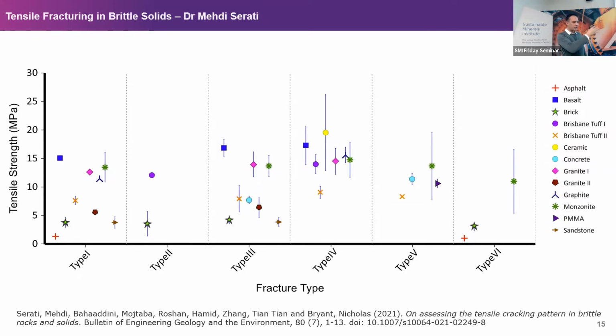So the question was, how come you get exactly the same type of product, like the broken sample, but in some of them the force at failure is 50% less. That's why we used a high-speed camera, and to our surprise, those samples that showed the lowest force at failure correspond to cases when the crack didn't start from the center, but rather started from one of the 2 ends. This suggests that although you may look at the sample, and you are not utilizing high-speed recording, you look at the sample, you break it, you get a single crack, it's all good, that's a tick. But the reality is how the crack is started, where the crack is started. It's not just the fracture; when and how the crack initiates make a big difference. In our study, it suggested it could lead to up to 40% overestimation if the initiation of the crack is not considered.